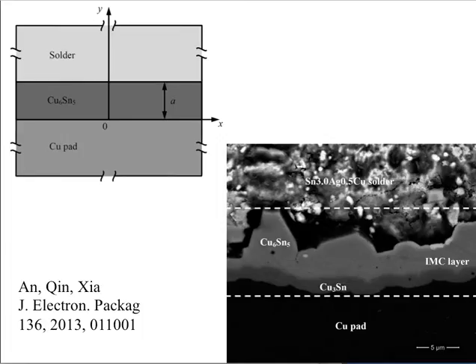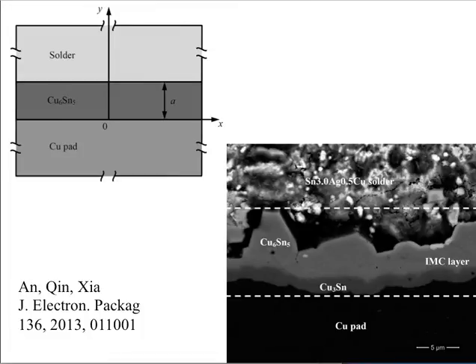In this case it is heat diffusion that is doing that. When we do soldering of electronic components, you get a reaction between the copper and the solder which creates intermetallic compounds, and the thickening rate of those intermetallic compounds is parabolic with time, because you are reacting tin in the solder with the copper and the diffusion distance increases between the copper and the solder. So parabolic kinetics apply to many scenarios in materials science, not just to steels.